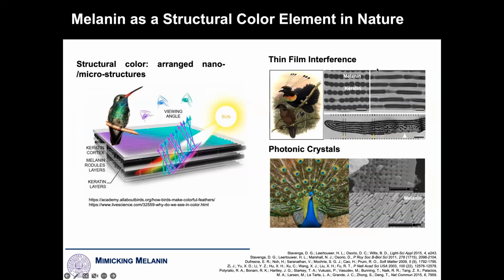This can come in the form of straight thin film interference, the way you would see if you have an oil slick in water on the ground at a gas station, which is highly unstructured, but the same kind of thin film effect, or in photonic crystals that, for example, lead to these spectacular color displays in peacock feathers. If you were to extract, again, the eye of these peacock feathers, they would be completely black particles. So again, none of that is pigment.